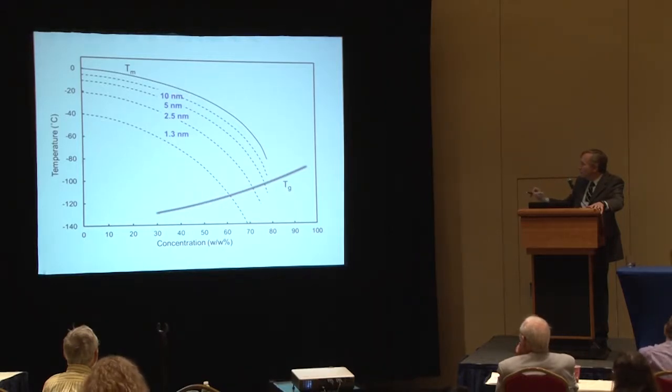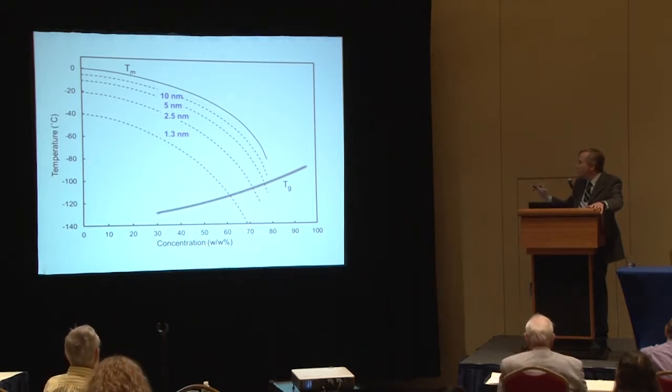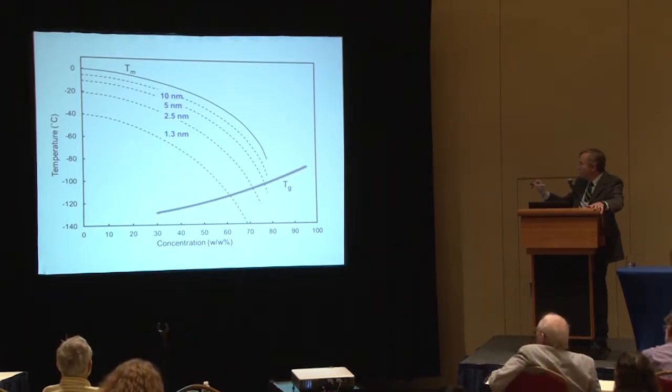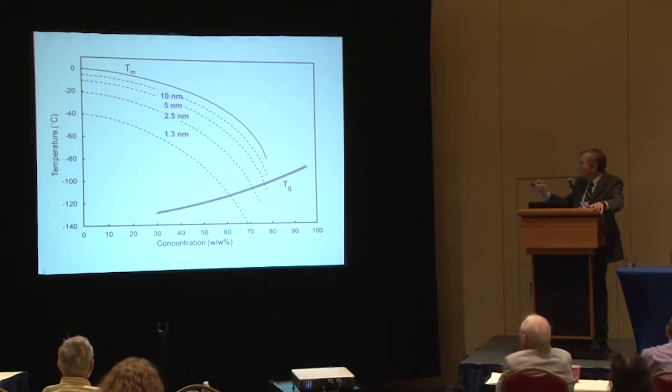What that means is that if ice nucleates and forms in a pure solution, free of any contaminants, it's actually impossible for ice to form in this region, because as soon as a minimal size ice crystal nucleates, like say 1 nanometer in radius, it's going to immediately melt.